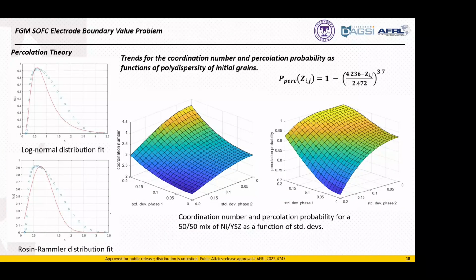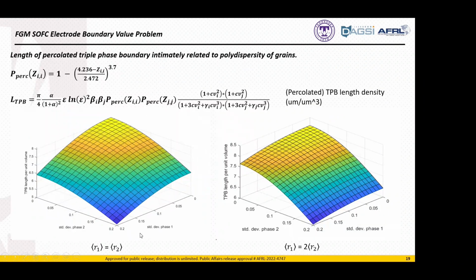grains. And then I've worked on some theory here which is really just relevant for the electrochemistry, but it enables us to go from the particle size distribution of the sintered electrodes to get back out the percolation probability and the effective ionic and electronic conductivity of the electrodes. And so these things will be functions of the polydispersity of the grains. And again, I know we don't have time to necessarily go through all this.